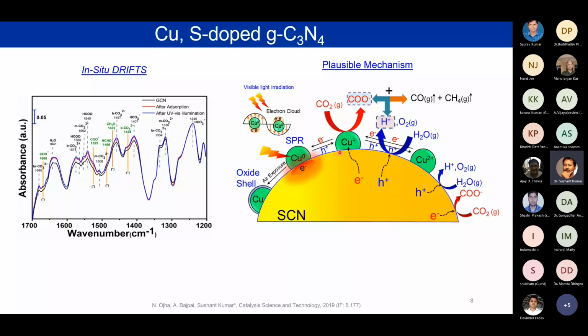And then what we do, we look at the Cu+, which I told you about, because of the in situ ESR results. We see that the CO2 transforms to COO minus, and then this H2O gives us H+. Oxygen should liberate, which we have not quantified in this work. And then this COO minus with H+ would give us CO and methane. So this was one kind of work that we have done. And then this SPR effect is there, which we don't deny. That would also be present in this kind of photocatalyst. So this was one of the works that we have done in 2019. As you can see, this was our first work.